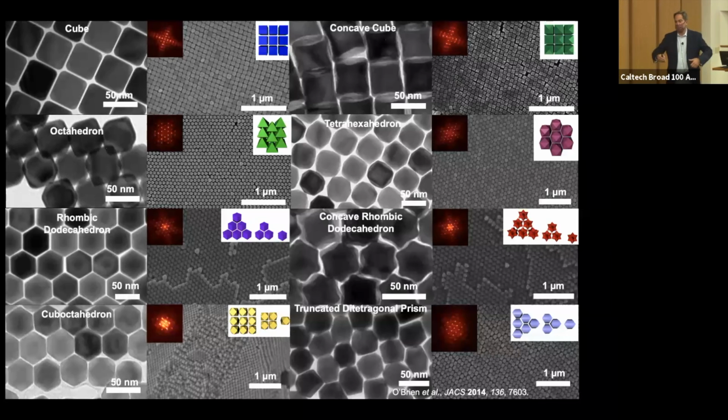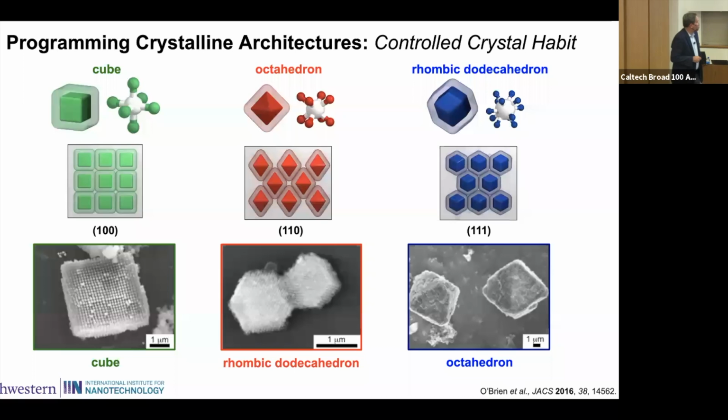We know that because when we let them dry, they want to crystallize naturally. They have no oligonucleotide on them. We haven't forced any interaction yet. But if we modify them, we can begin to test this concept of valency. So as I said, if I want octahedral valency, I take a cube-shaped particle, modify it, and now that directs the formation of a cubic lattice.